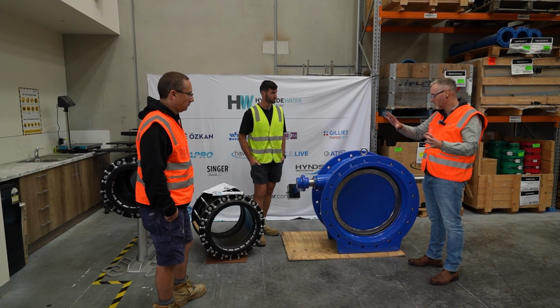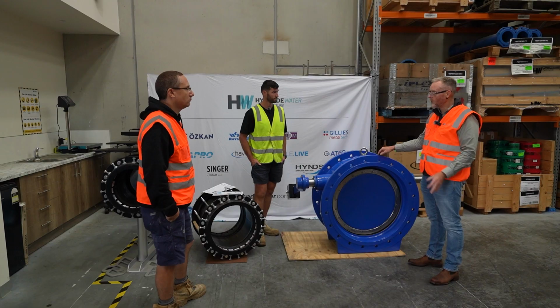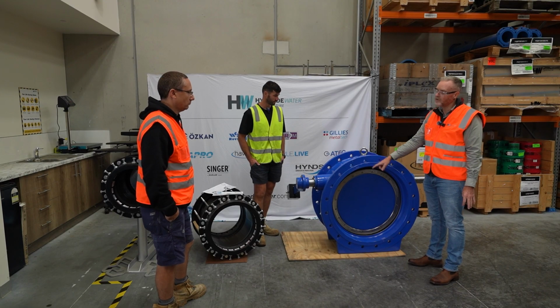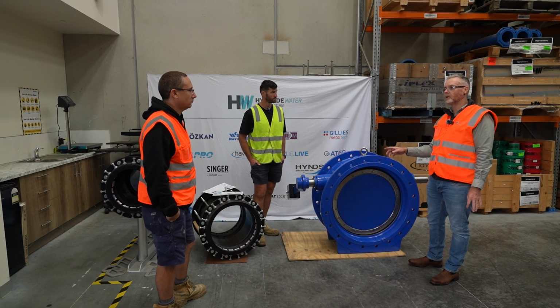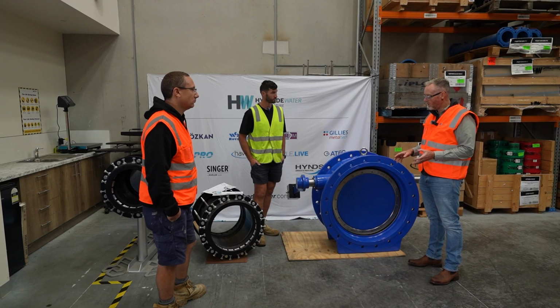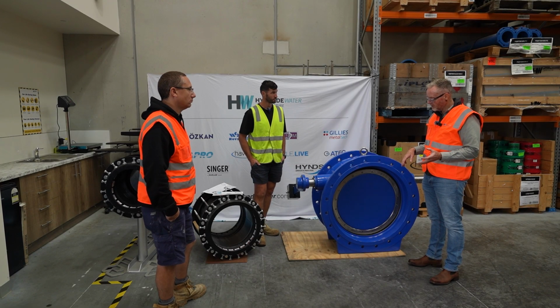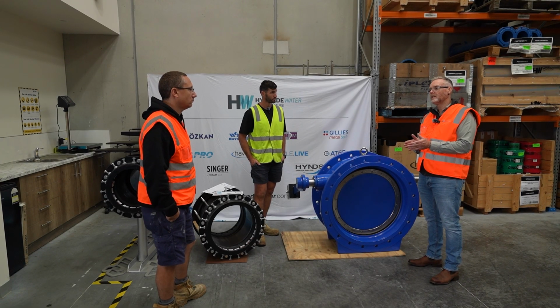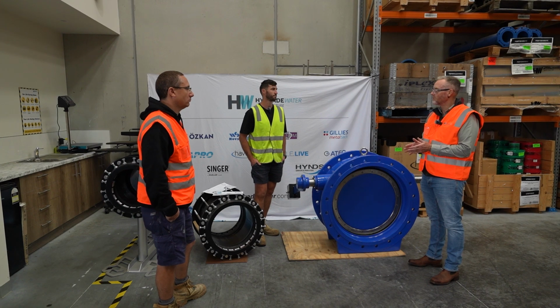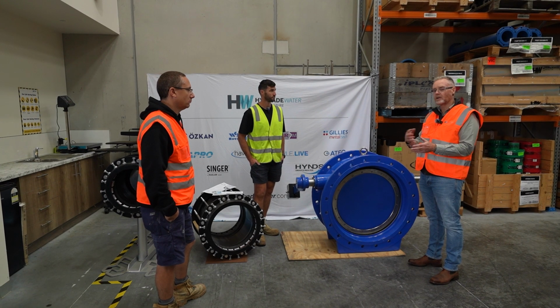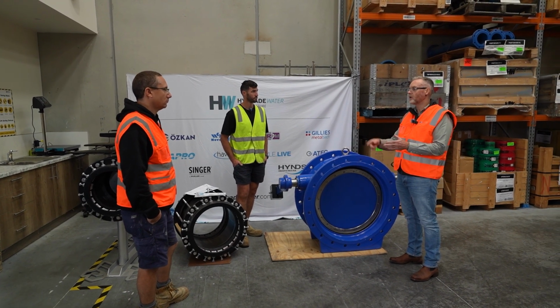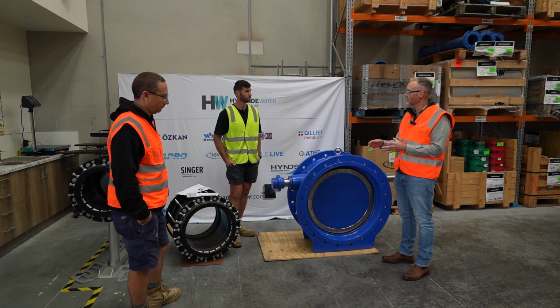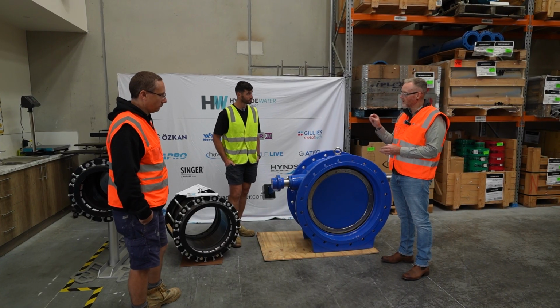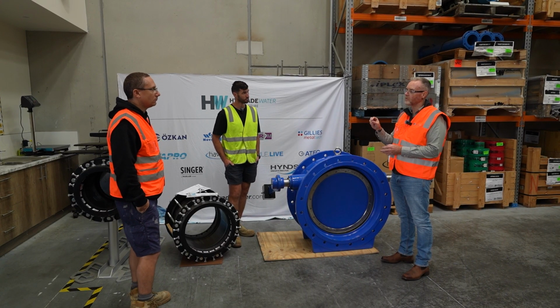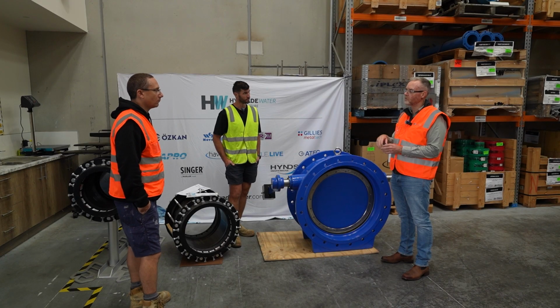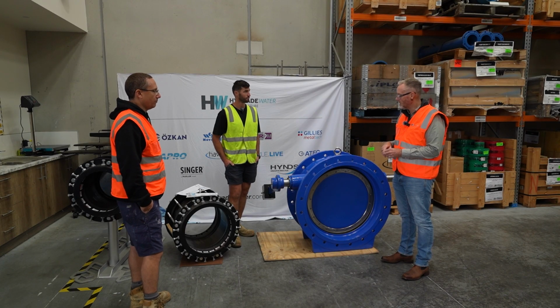Then we coat the entire valve with the coating, and then we micro finish the stainless steel seat back to how it is. The reason why that's important is because if you're painting up to a seat, you're always going to have voids. So we always want to paint, let it go off, and then micro finish back so that you don't end up with any voids. You only need one little grain of sand or silt to get in behind that, and it'll just destroy the valve in no time at all.